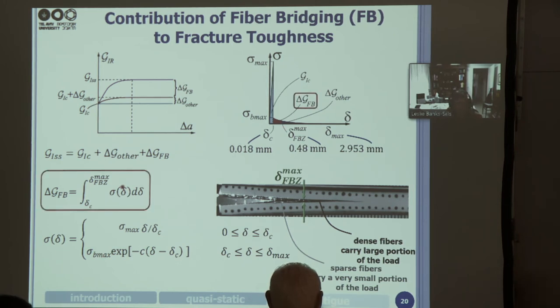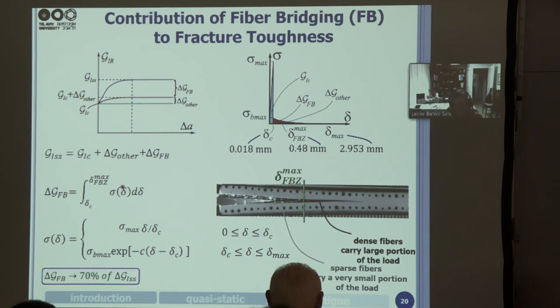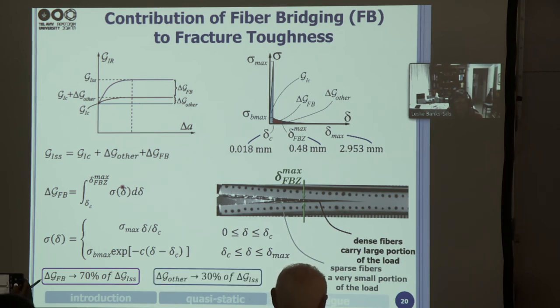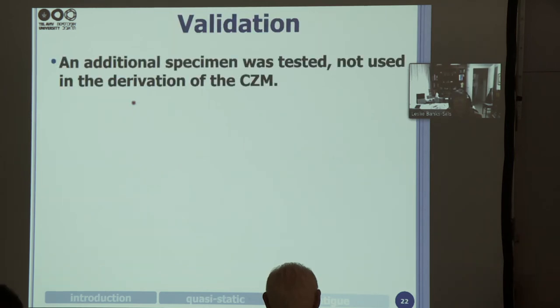We obtain the integral, and we find that delta G_FB is 70% of delta G_ISS, and delta G_other is 30%. So we claim that we have subtracted off the contribution for fiber bridging in the quasi-static test, and this is the net G1R curve.